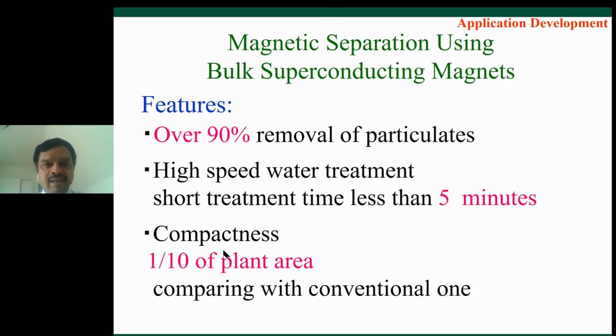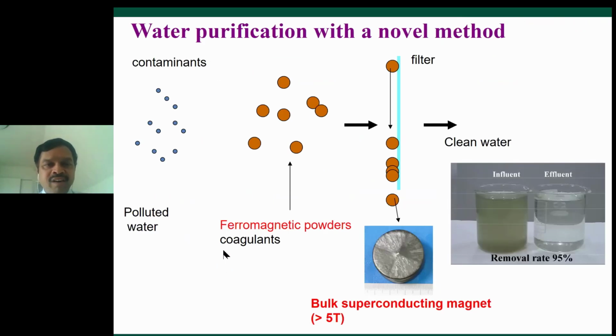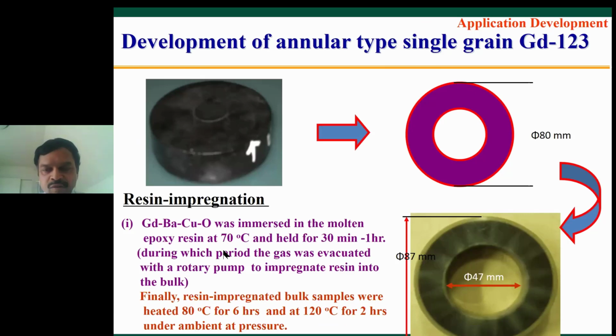And also magnetic separation with bulk superconducting magnets is very powerful. It has already been experimentally proven: over 90% particle removal, high speed treatment, and 1/10 floor area due to compactness. The main idea is that polluted water often contains ferromagnetic powder, which is very cheap. Then one can use a bulk superconducting magnet of more than 5 Tesla. As a result, one can get clean water. You can see the laboratory result, where the removal rate is 95%. It will be very useful especially for cleaning lakes and ponds. Even Saudi Arabia and India, so many countries have water cleaning as one of the major issues, like ponds and so on.